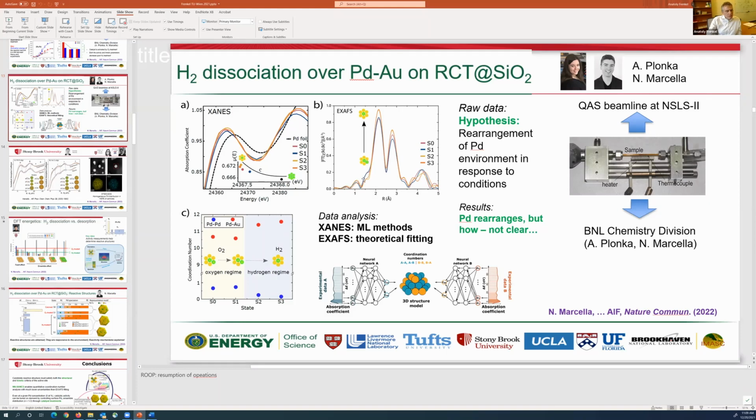It is maybe or maybe not consistent with the fact that under oxygen conditions, or right after oxidation, the signal is a little bit higher than after hydrogen reduction. But fitting it with oxygen is very speculative, and we couldn't find anything from that. If you get something from the fit that gives you a good fit, but with a huge error bar, it's really not informative for any purpose. I would just be more conservative and say we can't tell it, rather than say it's not there. I think we just don't have enough confidence that we can detect it.